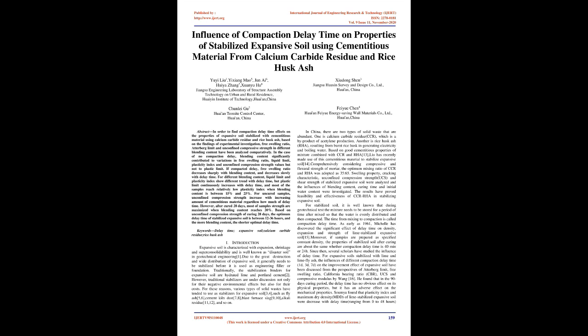Based on good cementitious properties of the mixture combining CCR and RHA, 13 Lu has recently made use of this cementitious material to stabilize expansive soil. 14. Comprehensively considering compressive and flexural strength of mortar, the optimum mixing ratio of CCR and RHA was adopted as 35:65. Swelling property, cracking characteristic, unconfined compression strength, UCS, and shear strength of stabilized expansive soil were analyzed, and the influences of blending content, curing time, and initial water content were investigated. The results have proved the feasibility and effectiveness of CCR-RHA in stabilizing expansive soil.